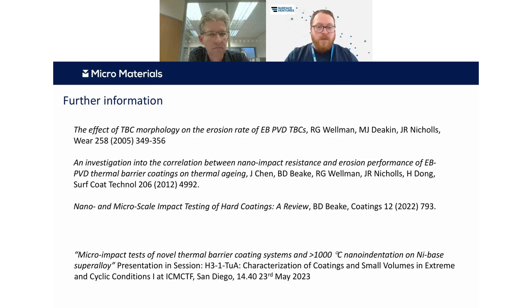Just whilst people are typing questions in, a quick one from me to get us started. You mentioned you're going to look at different coating types, microstructures, and novel coatings. Can you tell us anything about what types of structures or microstructures? Well, I think the interesting thing is to look at if we can combine retaining the columnar structure, but also with a degree of multi-layering in this plane as well. So it's that combination of those two types of structures, and we may be able to compositionally vary, have layers of more erosion resistant but thermally less good thermal conductivity layers. So there should be some optimization based around that.